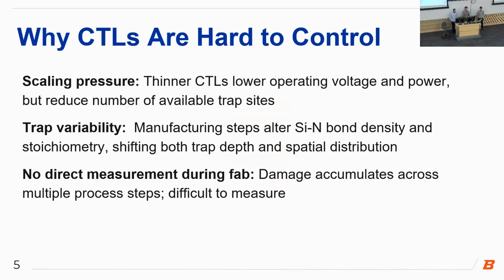So as these charge trapping layers get thinner, the operating voltage and power required decrease, which is a good thing, but the amount of available trap sites also decreases, which makes it harder to retain information for a long time. And any manufacturing steps that alter this bond density and stoichiometry shift both the trap depth and the spatial distribution of these charges. And because these processes are sequential, it's hard to know which process affects the films with what damage.